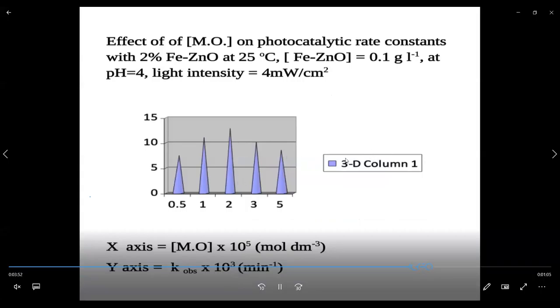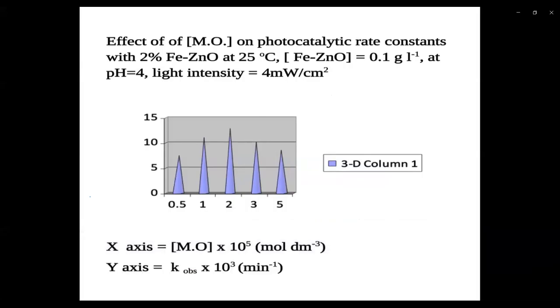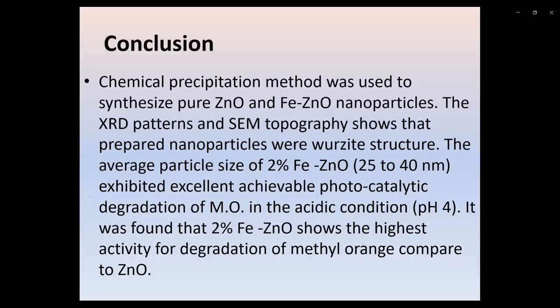The degradation rate was examined keeping the photocatalyst amount constant at 0.1 gram per liter. So at first the degradation rate increases and reaches the maximum. Afterwards, it declined as the methyl orange quantity increased. 2 into 10 raised to minus 5 mole per dm cubed is the limiting value. Afterwards, the degradation rate constant decreases.